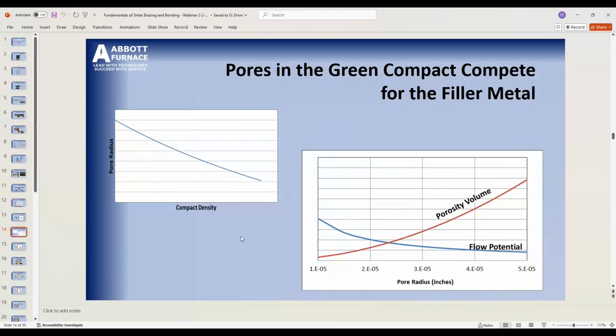Well, gap's important when we put the parts together, but in sinter brazing, we have another problem. All the porosity in our parts act just like little gaps, and they want to steal the filler metal away. So how do we keep that filler metal from going into the gap but not infiltrating the part? Okay, well, what we have to realize is as the density goes up, the pore size goes down. As the pore size goes down, look at this, it wants to steal that filler metal even more. That flow potential goes up, right? So smaller pores, higher density, that means that part wants to steal the filler metal from the gap.